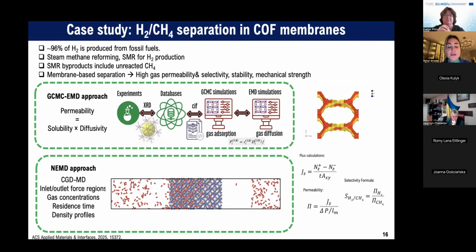In our community, we generally do the first modeling I am showing here right now. You perform your experiments and have the XRD data, you characterize your material, and then we need CIF files. You put the CIF files in, generate the structure, and at the end of a GCMC simulation, you have gas adsorption data. In equilibrium modeling, you directly use the gas uptake data inside the structure, and the gas molecules are diffusing inside the structure. This is equilibrium molecular dynamics. Combining GCMC and EMD results, we have the permeability data, and the ratios of permeabilities give you the selectivity. This is a very well-known and well-established method that we use in the literature.